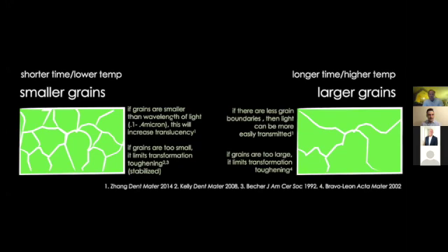As far as talking about some of the stuff that's going on in the lab, when sintering occurs, so sintering is putting it into that furnace and heating it up so that it turns from that chalky looking thing to the crowns that we know and love. The amount of time and the temperature at which you sinter things is essentially causing grain growth to occur. The grains start off small and then they get bigger the longer or the hotter that you sinter a zirconia.